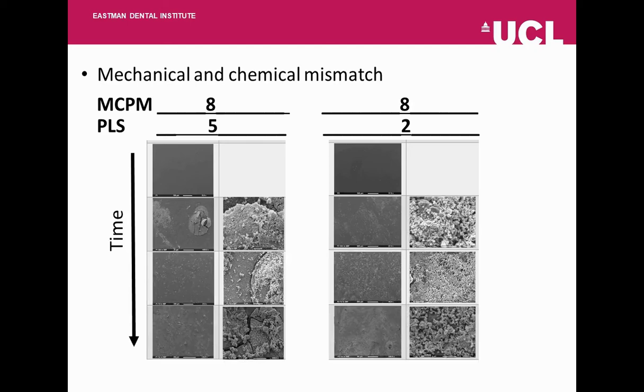Here are the two groups with 8% monocalcium phosphate and varying levels of polylysine over a period of 1 month. Images are taken using a scanning electron microscope. And the first image at the top for each group is what the disc surface looks like prior to being placed in simulated body fluid. The images on the left for each group are low magnification, and the images on the right are high magnification.